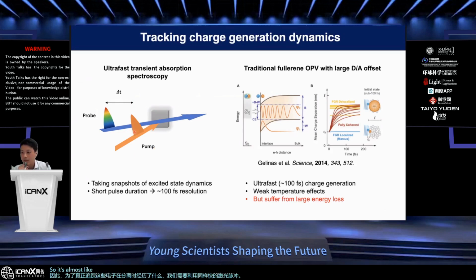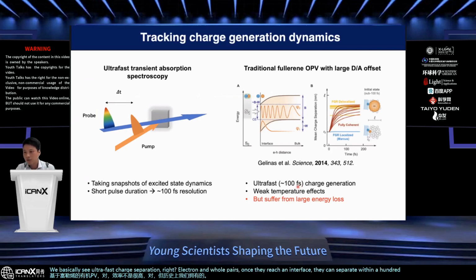So it's almost like taking a video. In order to observe really fast moving objects, we need to have a very quick frame rate. This is exactly the reason why, to track these really fast electronic processes, we have to use really fast laser pulses. Now, by doing so, we can apply this technique to look at a variety of different materials. Traditionally, if we look at fullerene-based organic PVs, which are not very efficient, we see ultrafast charge separation. Electron and hole pairs, once they reach an interface, can separate within 100 femtoseconds, a super fast time scale.